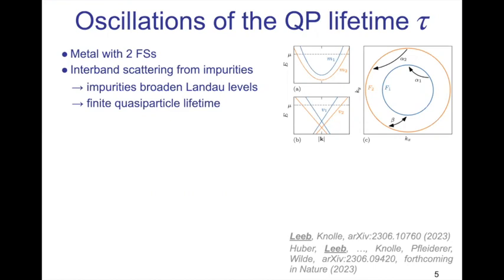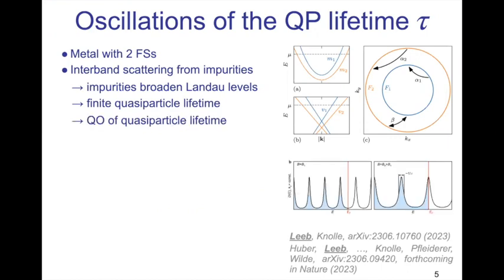This is the point. Now, if you evaluate it a little bit more carefully, you will see that actually the quasi-particle lifetime is not a constant with respect to the magnetic field, but it will acquire quantum oscillations as well.